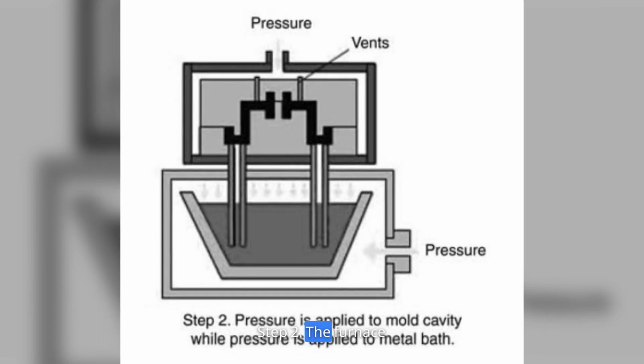The following describes the basic counterpressure casting cycle steps. Step 1. The die closes to initiate the casting cycle. The mold chamber is set up to seal at the same time as the die halves. Step 2. The furnace is pressurized at the same rate as the mold chamber.